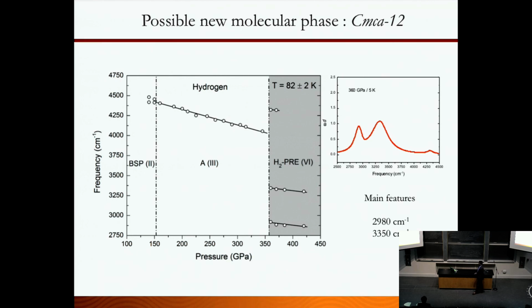The problem with the theory is that it's difficult to get this calculation right because of the anharmonic nature of the hydrogen. So you have to do the anharmonic correction. If you do that and the zero-point energy corrections, you probably can bring it down, make this one softer. And probably this will be the same CMCA12 phase that theory has predicted. In terms of how it behaves under pressure, it's very similar to what we observe. It has the same differences and the same pressure dependence. So it's not exactly the CMCA12, but that's the best guess we can give.